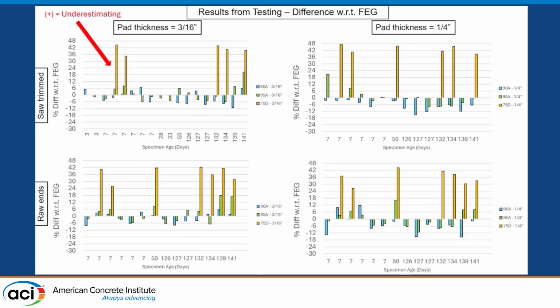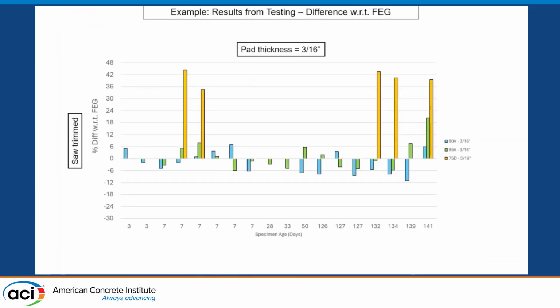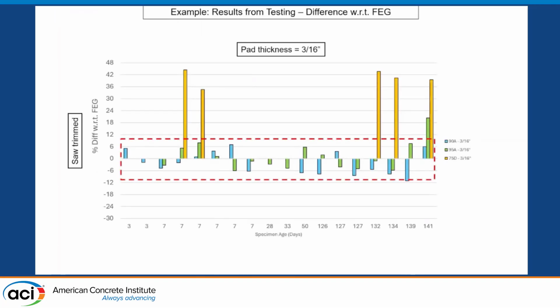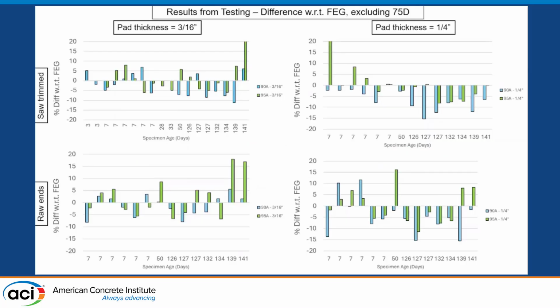And so here's another plot that shows the percent difference with respect to the fixed and grinded condition. Anything that's positive is severely underestimating the results, and anything that's negative is overestimating the results. And as we can see here, the 75D is off the charts. I mean, it is above 30% with respect to fixed and grinded condition in almost all cases. And the thing I'd like to note, though, in the majority of our cases was the 90A 3/16ths and the 95A 3/16ths was almost always within 10% of the fixed and grinded condition. So this was proving our thoughts before.